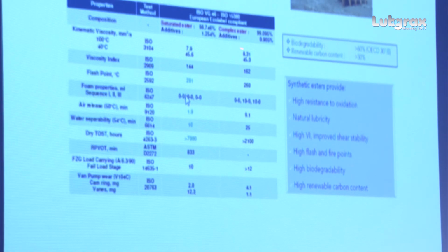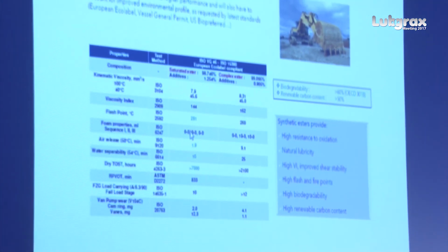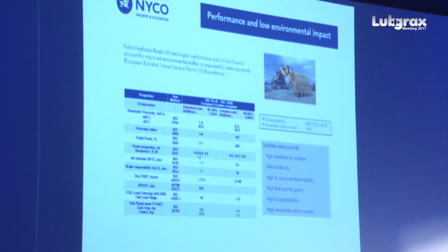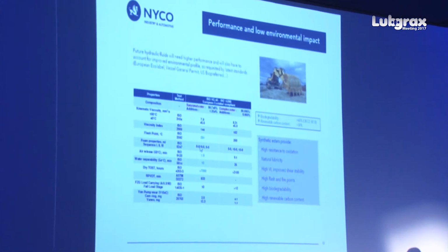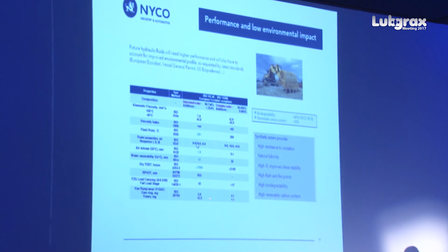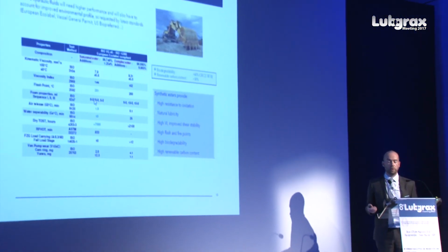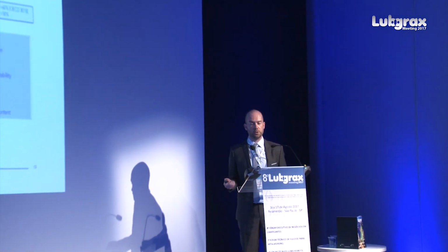So you have on one side saturated, that's neopolyol ester, and here complex ester. We made tests regarding the ISO 15380 standard, which is a common standard for biodegradable eco-label hydraulic fluid. And a lot of these tests show that esters can bring very good technical performance without compromising on the environmental profile. It has high resistance to oxidation, good lubricity, we can have a look in detail, but also high flash point, which can be required for some application, and very, very good environmental profile.